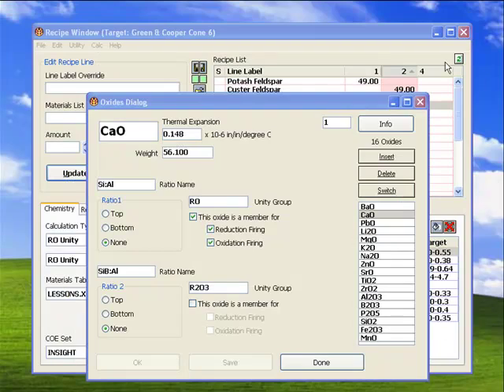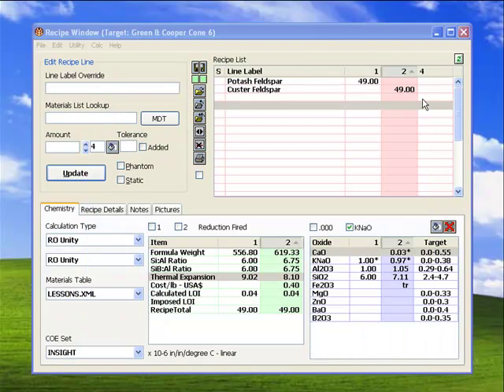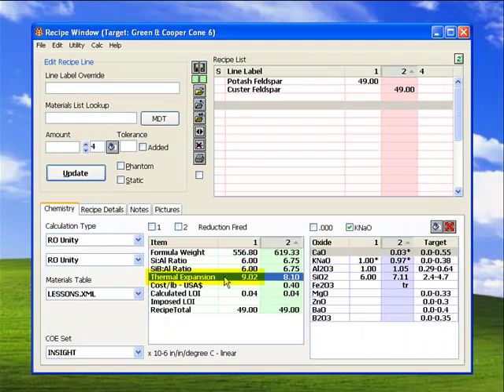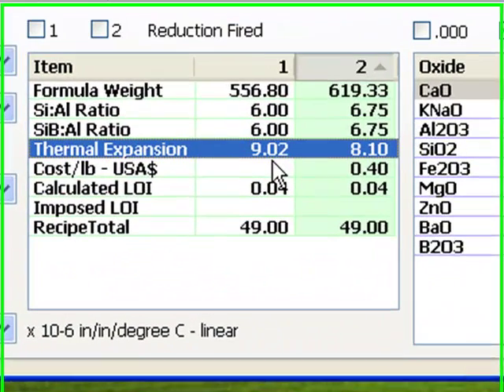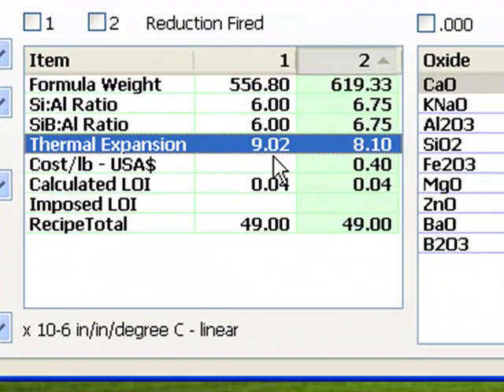Notice also the expansion for theoretical potash feldspar in column one of the calculated items list. This is really high. I use the Insight standard set of thermal expansion numbers and over the years I've found that common stoneware glazes need to be below about 7.5 to avoid crazing. Of course, your circumstances might be different, especially the clay bodies you use. As an experiment, try making a glaze from pure feldspar and fire it on a sample at cone 8 or 10 and be ready for the worst crazing you ever saw.